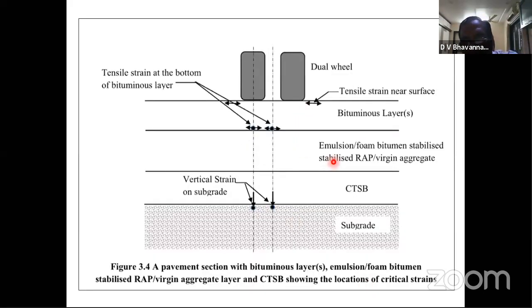Also, one more option is recycled asphalt pavement. RAP means recycled asphalt pavement. It is mixed with some virgin aggregates to satisfy the required gradation, and bitumen or emulsion or foam bitumen is used to supplement the bitumen requirements. Suppose in the RAP we are getting about 3.3% of bitumen. Then if the actual requirement is 4.5%, we have to add 1.2% bitumen in the form of emulsion or foam bitumen. And we have to add some aggregates to satisfy the requirements either for the DBM or bituminous concrete.